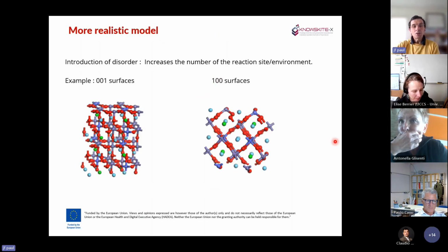Just to show you the system on which we are working now. So we started from the same lanthanum iron bulk crystal, but we define a larger cell which allows more disorder for the position of the cobalt on iron, and also more disorder for the position of strontium on lanthanum. Doing that, we will increase the number of reaction sites and reaction environments and see how things are working. So we have started to do some tests on these classical surfaces, and we also want to see what happens for surfaces with higher energy, which may or may not, we have to check, be responsible for the activity of the system. And this type of model will also be used to study the diffusion of the oxygen inside the bulk. And here we have quite a lot of possible environments, which is important to define the easiest pathway for the oxygen diffusion.